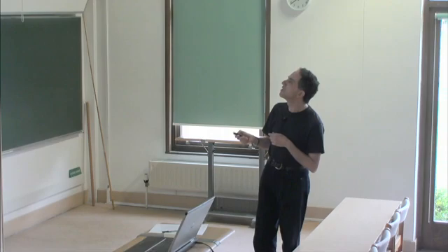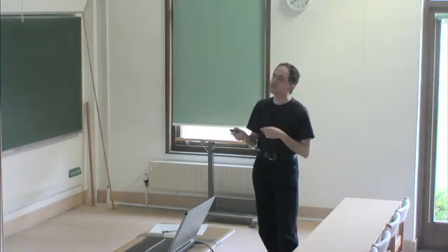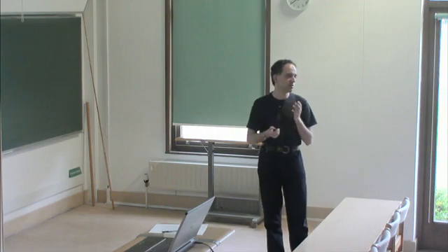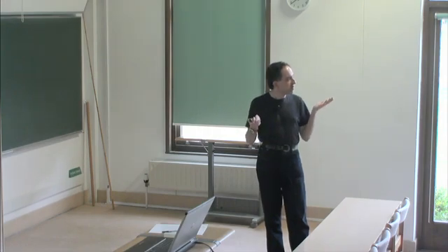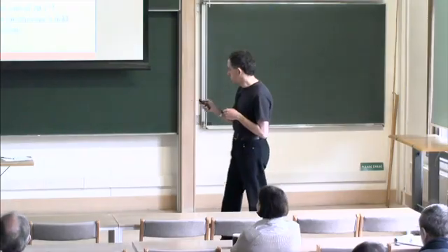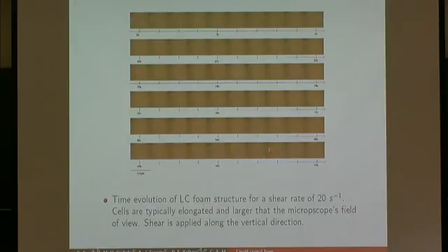And one of the results that I'm going to describe later is that now this is clearly non-equilibrium. Well, it's non-equilibrium because any foam is non-equilibrium, and now I've put it under shear. And one of the interesting features now is that your angles will in general not be 120 degrees. They'll be a little different, and how different they are will depend on whether your bubble is large or small, basically.